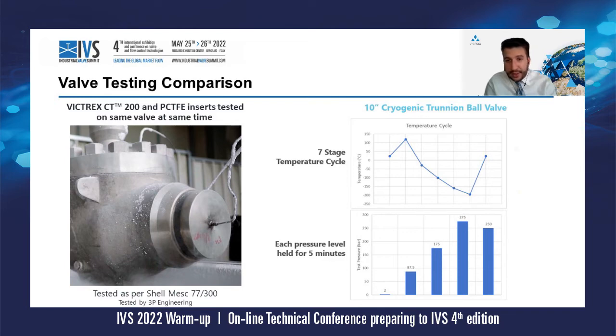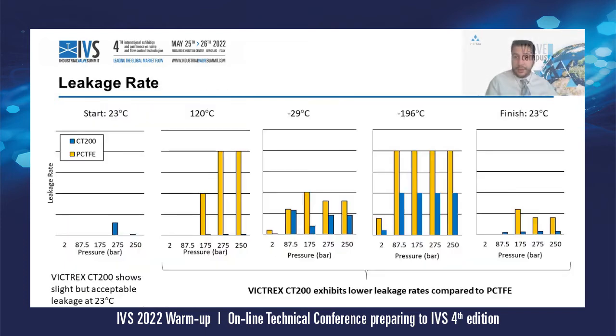We couldn't go higher because there was a PCTFE insert inside, and PCTFE cannot withstand, as we said, temperatures higher than 120 maximum. And we made the test as per the Shell MESC SPE 77/300, which allows for very low leakage rates. And we measured the leakage and the torque. So we noticed during the test a lower leakage over the whole range of temperature at each pressure. So despite there being some leakage, it was acceptable from minus 196 up to 120.